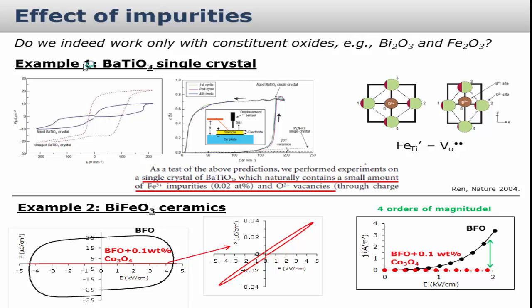Another example is BiFeO3. This is a case from our lab. For example, in this black curve, we try to measure polarization as a function of electric field. You see this sort of balloon shape here, which just tells you there is a huge contribution of an out-of-phase component in the polarization response, which is related to conductivity. And then you add just 0.1 weight percent of cobalt. We got to this accidentally. We got cobalt during processing, and then we just repeated to see if this was exactly the case. And you see how, with just this small amount of cobalt, we can measure a normal dielectric response with a bit of hysteresis.